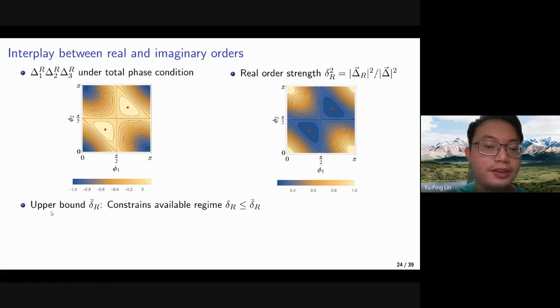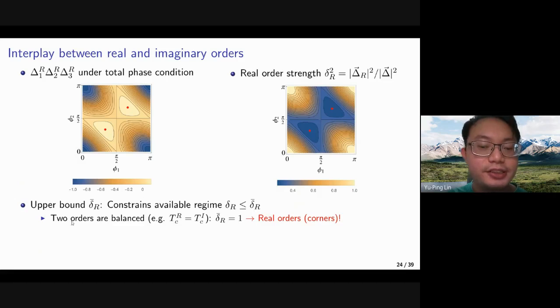So we could define an upper bound for the strength so that we could constrain the available regime in terms of the real order strength. The first case is when the real and imaginary orders are balanced, that is, for example, when they have the same critical temperature. The maximal real order strength we could have is 1. That is, we could have a purely real order.